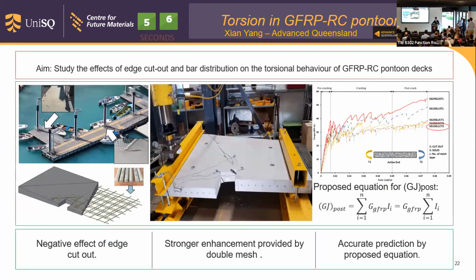I work on torsion in GFRP reinforced concrete pontoon decks. Pontoons always suffer from torsion because of wave actions. The inclined torsional crack will initiate from the corner of the edge cutout, which is a compulsory design for pile fixture purposes. Eventually, the steel reinforcement inside will result in corrosion. GFRP reinforcement can permanently eliminate the corrosion issue in this case. However, the torsional behavior of GFRP reinforced concrete decks has not been addressed in any Australian or international design criteria.